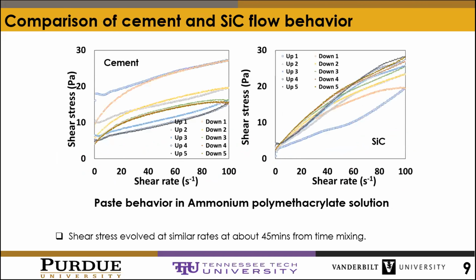Here I briefly compare the rheology of cement against that of silicon carbide. In the first 45 minutes of mixing, while cement paste transits from thixotropy to antithixotropy, silicon carbide paste transits from antithixotropy to an unstable mixed mode of thixotropic and antithixotropic behavior, attributed to their different initial conditions of structuration immediately after mixing. Also, results suggest that flow curves for cement paste in the ammonium polymethacrylate, wherein hydration is occurring, evolve to a similar value of shear stress when compared to the silicon carbide.